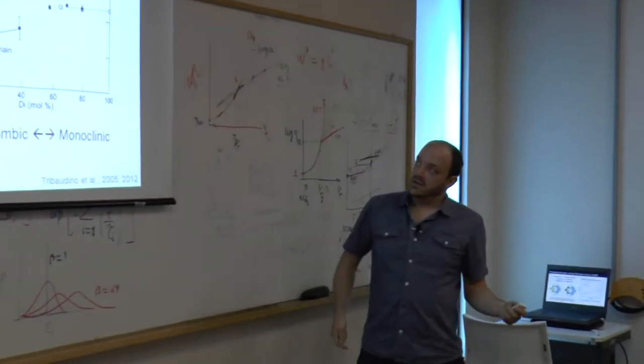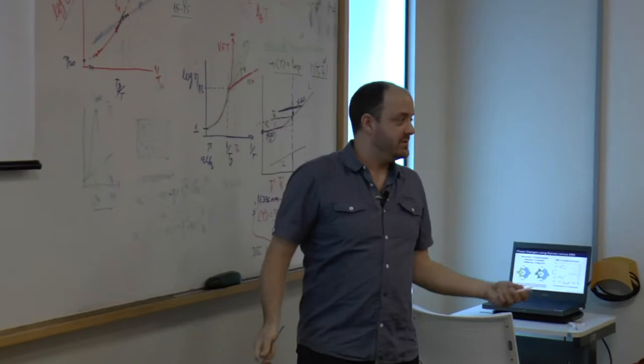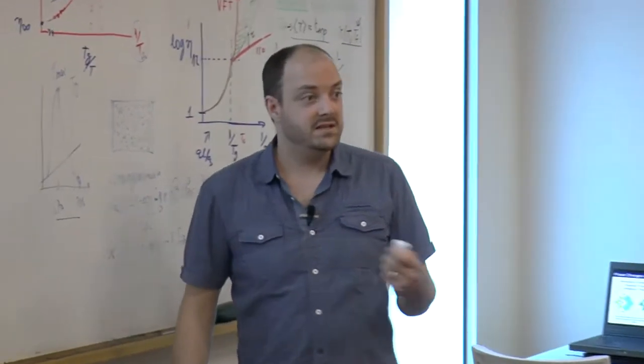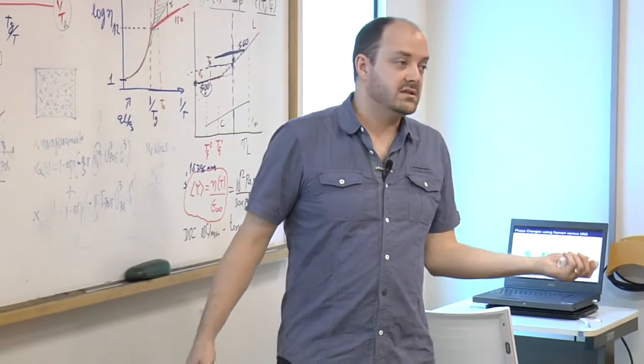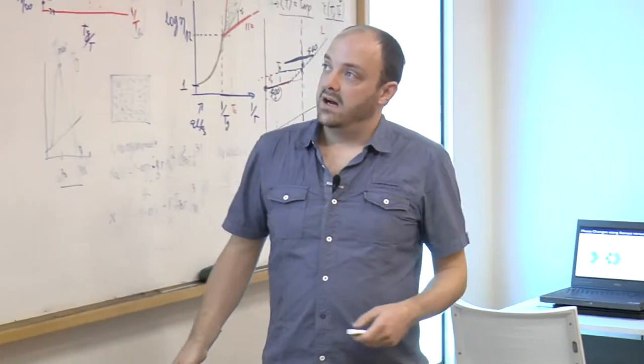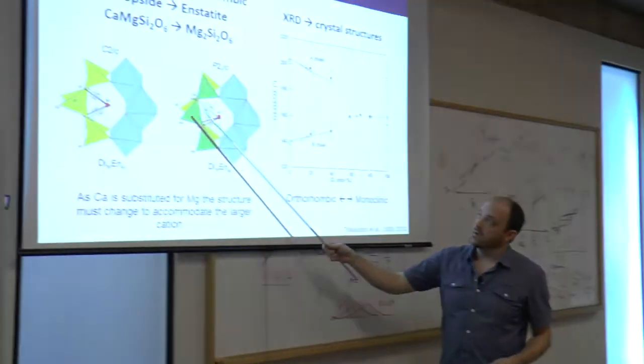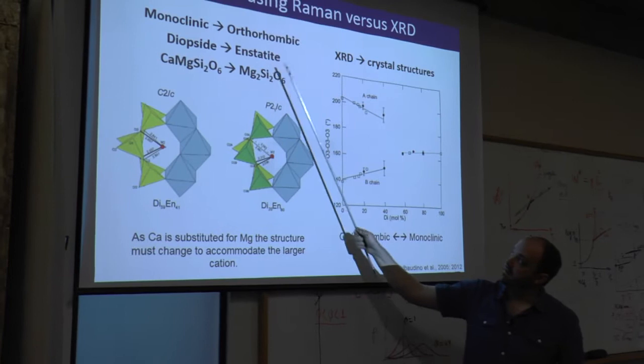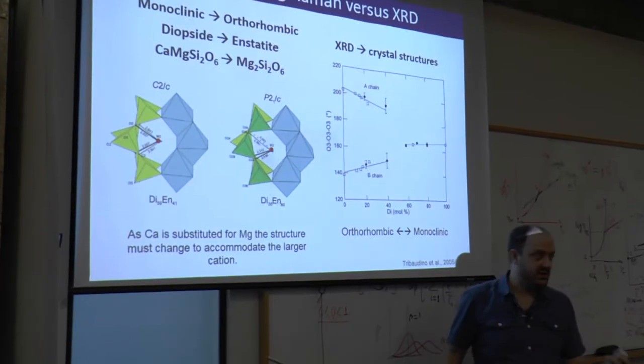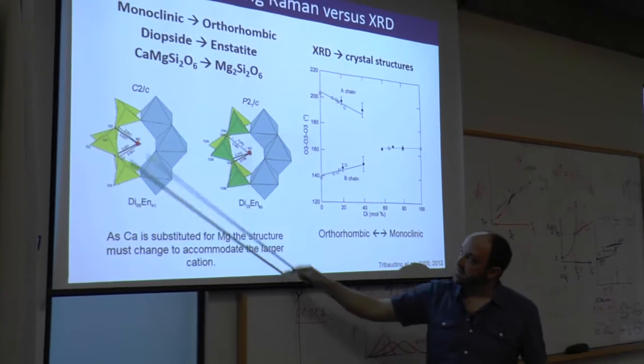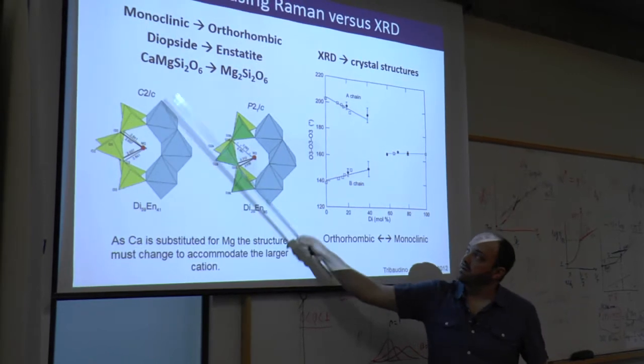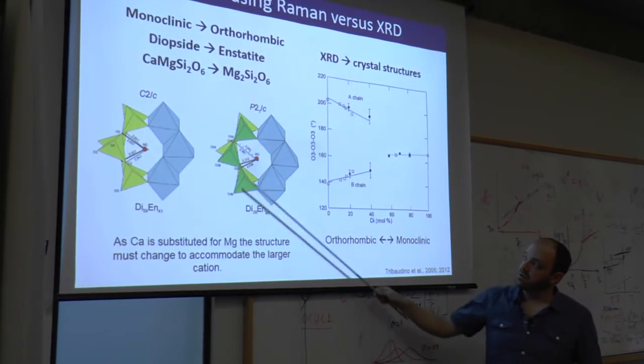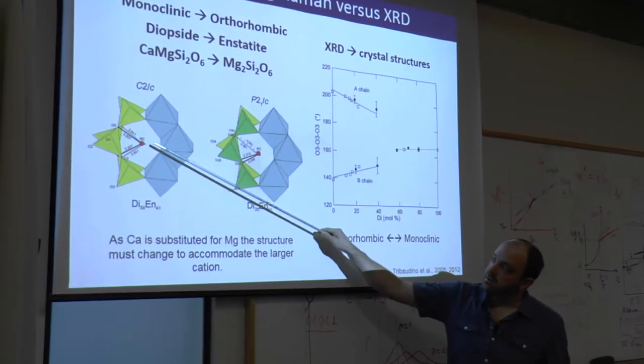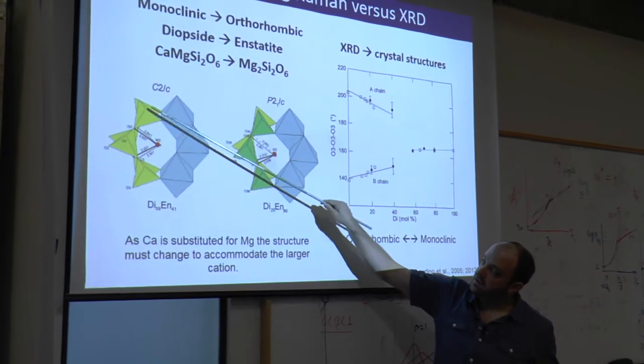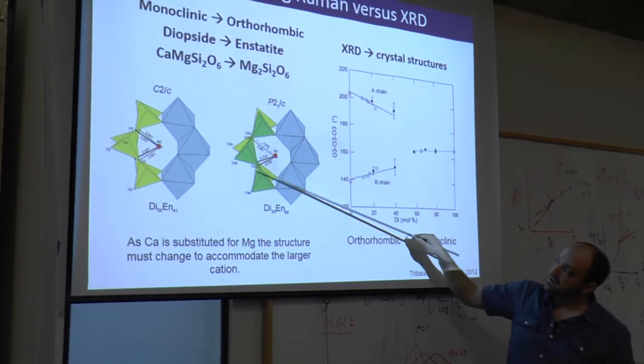Another thing, I know you guys are mostly glass people, but in case you have different crystalline phases in your glass ceramic, you can also look at phase change. This is an example I'll quickly go through, from diopside to enstatite. These are minerals now, not glasses. And the biggest difference in the two structures, whether you have a monoclinic or an orthorhombic structure, is actually the kinking between this chain of silica tetrahedra versus the other one.